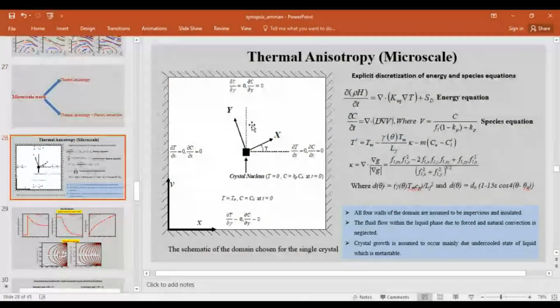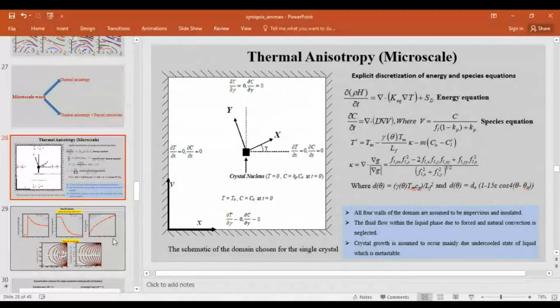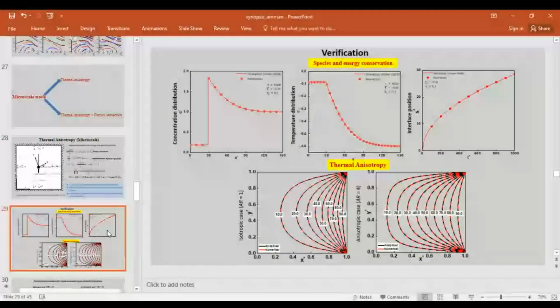Here you can see the schematic of the domain, right? Here we have impervious and insulated conditions on all four walls. In order to form a crystal seed, we place a nucleus here, and there is dendrite formation. These are the governing equations, energy equation and species equation. These are the assumptions I have taken. Verification has been carried out with the work of Waller, where we compared the concentration distribution, temperature, and the interface position.